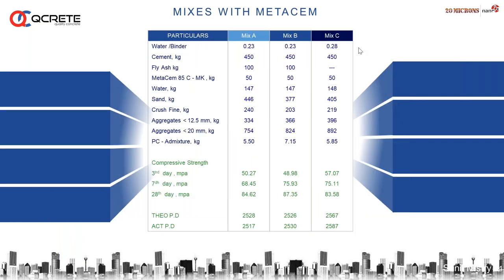The third part I can explain, this is the third series where we conducted some trials. Here we check all the parameters, right from controlling the flow, controlling the water cement ratio, keeping the cement of 450 constant for all three. We added fly ash, and at a consistent level, we added 50 kg of Metakaolin here. You can see here, we used PC-based admixtures where in trial A, we added 5.5. In trial B, we added 7.15, and in trial C, where we have not added the fly ash here, only Metakaolin and the cement is mixed here.